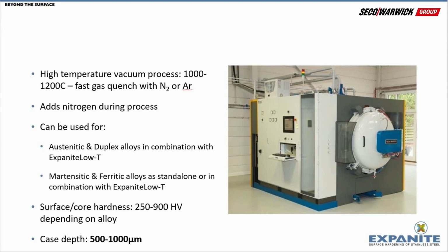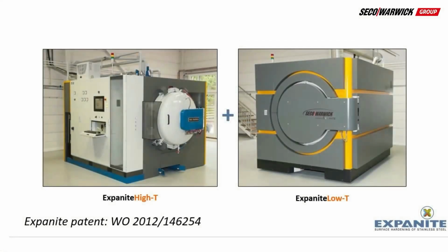Temperatures are up around 1150 degrees C or so, and we're introducing nitrogen here, only nitrogen, and we are quenching very fast. And if you combine those two processes, you get what we call Super Expanite. So Super Expanite is really a combination of the high temperature process followed by the low temperature process. And it brings me back to what I told you about before, that we would very much like to get rid of all those cold work surfaces, and we achieve that in the high temperature process.